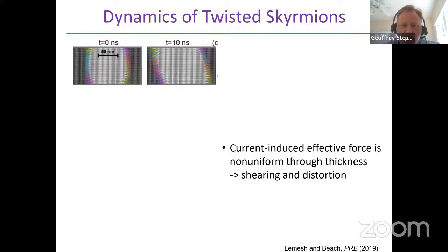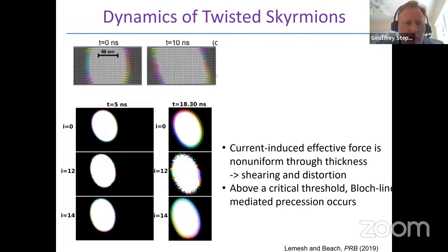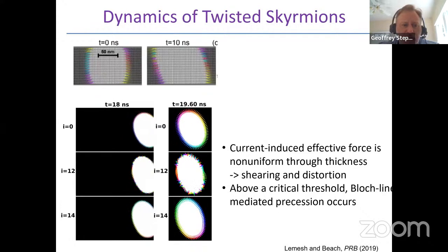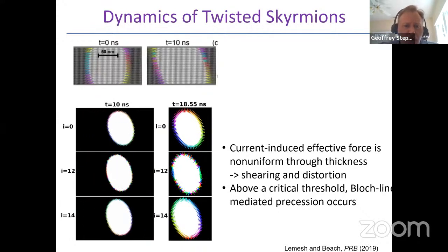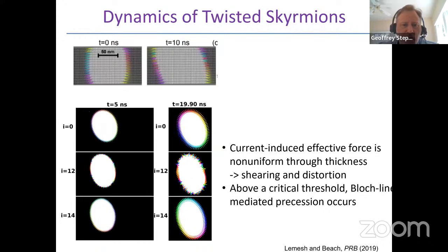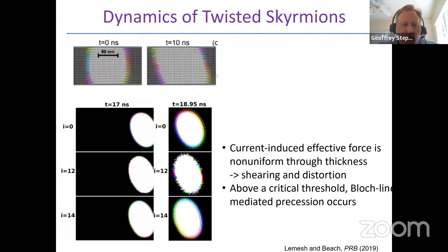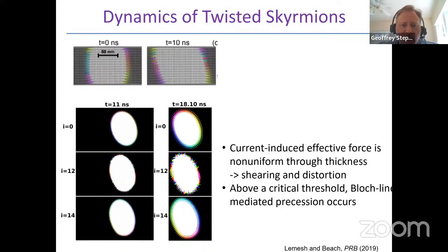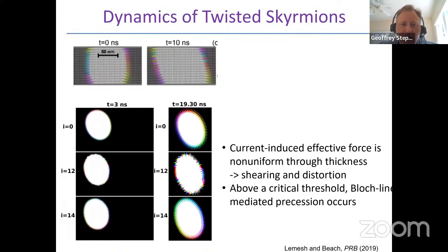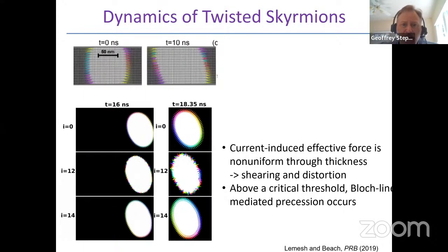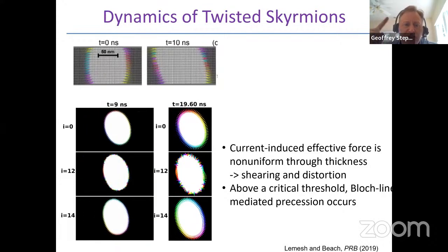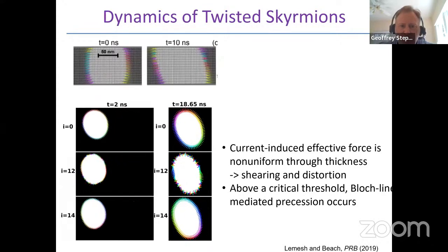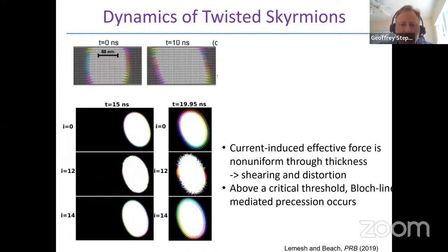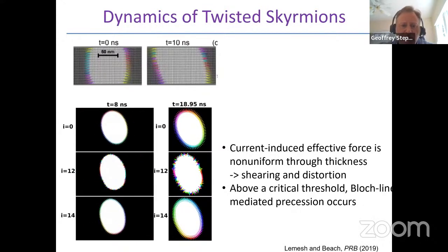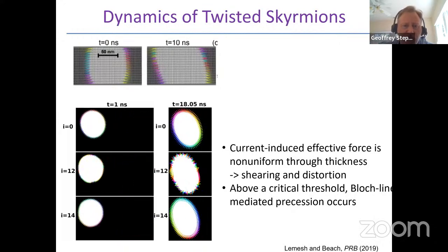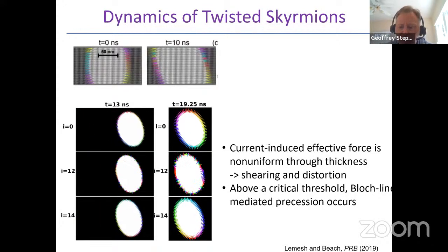And one can see the same kind of thing with skyrmions. This is a simulation that shows a multilayer skyrmion, and the three rows at the bottom show different individual layers within that skyrmion. And the one that corresponds to layer 12 here is where that node is statically. So statically the magnetic skyrmion in that layer is Bloch, but the stiffness between Bloch and Néel is very low. So at quite a low driving current, and therefore at a very low velocity, there are Bloch points that form, and that slows the progression of the entire skyrmion in a structure.